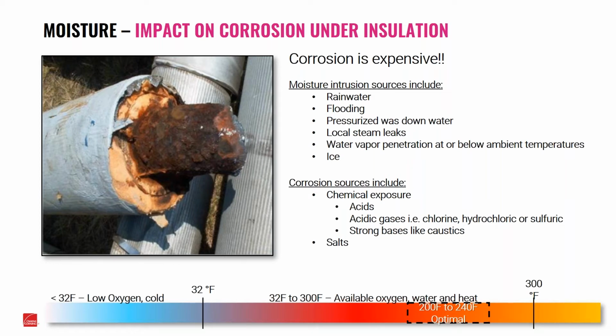We also have some other things we have to consider too, things like chemical exposures for both acids and bases, and salts. And maybe just one word here. I think a lot of times we tend to think of rainwater as being distilled water, not containing any chlorides. However, depending on where you're located, and depending on what kind of water you have available, you might have water intrusion from a freshwater source, but it actually contains chlorides. So any chlorides that are in the ambient air are going to get into your system. Even though we have corrosion tests that look at taking distilled water going through that insulation down to that pipe surface, they're using distilled water in that test. So if you're taking rainwater or water that has chlorides in it, and you're adding that onto there, your corrosion rate is going to be much higher. So again, another good reason you want to keep moisture out of your system.